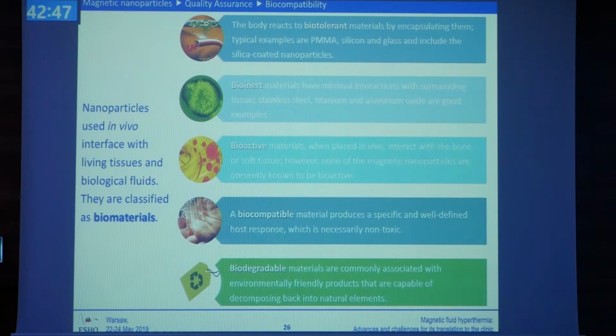So we have biotolerant materials. This happens, for example, for PMMA or silicon and glass nanoparticles. What happens there is that the body reacts by encapsulating them, and then they remain without any problem inside the body. Then you have bioinert materials, like the ones we have in passive implants. This is stainless steel, titanium, aluminum oxide, etc., which means that there is no interaction between these materials and the surrounding tissue. Unfortunately, it's difficult to create nanoparticles with these metals, and they don't have any magnetic properties anyway.